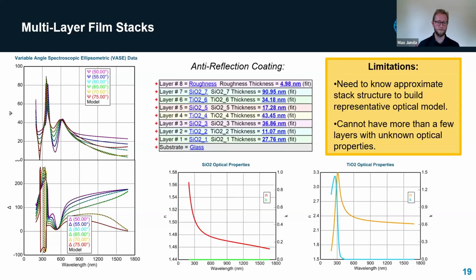So in order to actually model this, we did have to know ahead of time how many of these alternating layers are even present. If this was a completely unknown multi-layer film stack, I would effectively be guessing on how many layers do we think they are and what could they possibly be. So this means that it requires some knowledge before we start of what's physically present there. We don't have to know with great accuracy what the thicknesses are, but we at least need to know the configuration of the layers. And then the other thing is, if this was the same film stack, but every single layer was a completely different material and we had to be fitting the optical properties for it, that would be asking too much, and there would simply be too much information for us to determine layer thicknesses accurately.